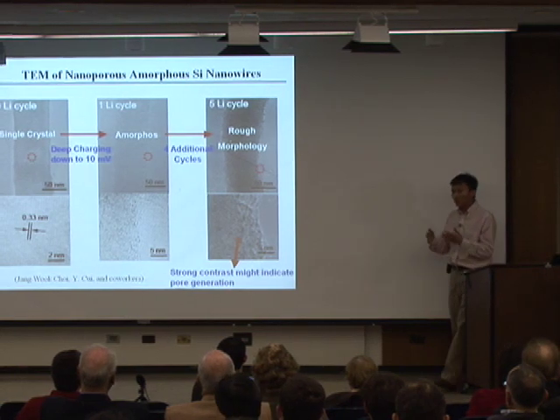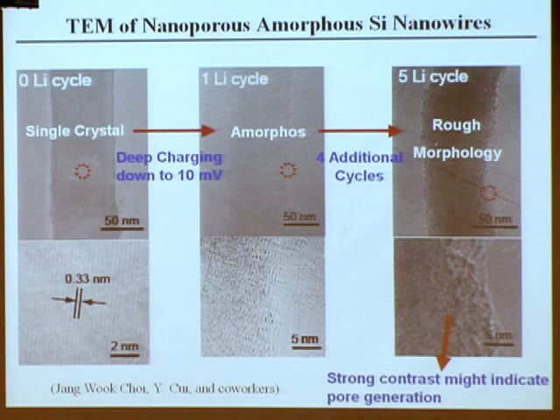But let's look at the structure a little bit. This is a single crystal silicon nanowire. This is after one lithium-ion cycling. So you push lithium in, you take lithium out. You go look at them under a transmission electron microscope. Well, this is single crystal. You see the lattice plane. This looks like it becomes amorphous now, but you don't see a lot of feature yet because the pore sizes are so small. So it's not really that visible on the transmission electron microscope.